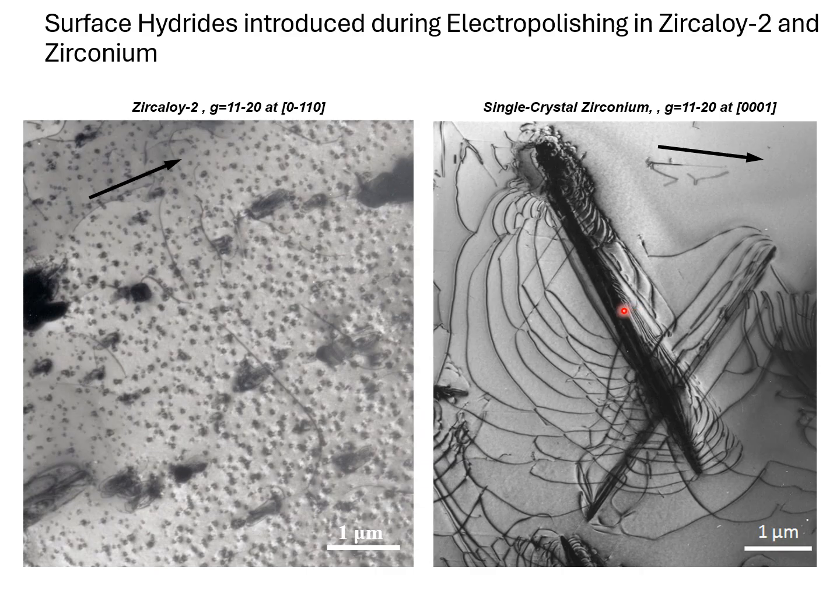If the chemical stress of the hydrogen at the concentration it exists at is higher than the yield stress of the material, you will get some deformation. The deformation typically occurs when the chemical stress driving the precipitation, and it's a real stress, is higher than the yield stress of the material.